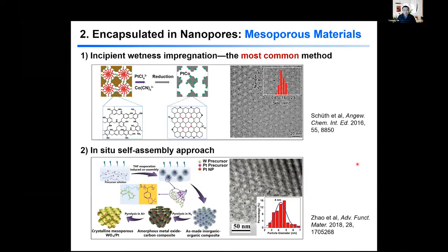Okay. And so we also have other ways to encapsulate nanoparticles. For example, we load them into mesoporous materials. And in this case, people use impregnation method. This is a very typical one for introducing materials into mesoporous materials. So people use, for example, surfactant assemblies as a template to produce a polymer matrix, which is porous because of these surfactants. And then they use impregnation method to introduce bimetallic precursors into the pores. And then after reduction, we end up with platinum cobalt bimetallic catalyst particles supported by this mesoporous carbon network.